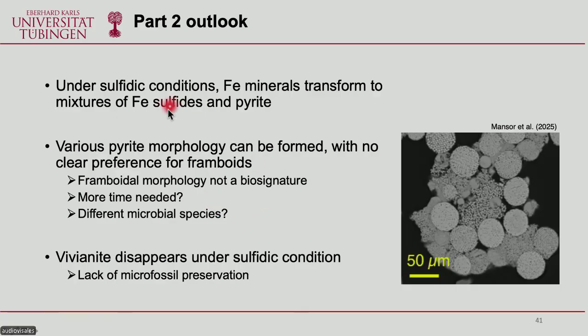We have shown that under sulfidic conditions, iron minerals transform to mixtures of iron sulfides and pyrite. And we can form different pyrite morphology, but no clear preference for framboids. So at the moment, our conclusion is that framboidal morphology is not a biosignature. But this brings more questions. Do we need more time for them to grow to larger sizes? Or maybe we need to use different microbial species. And another thing to consider is that we did form vivianite, but they disappear under sulfidic conditions. And this can have implications to part 1 of the talk, in which you can have microfossils preserved with the vivianite, but under sulfidic conditions, they get destroyed.